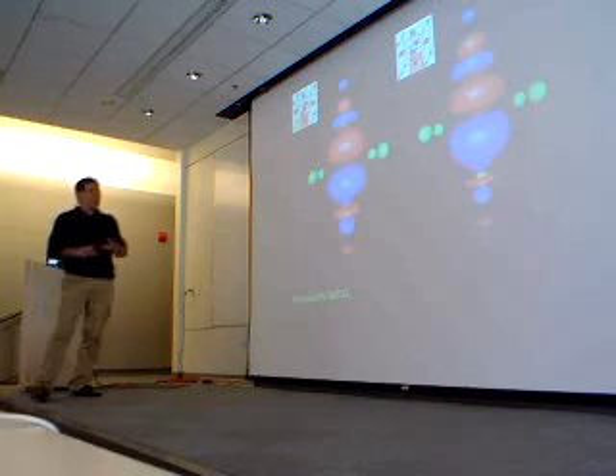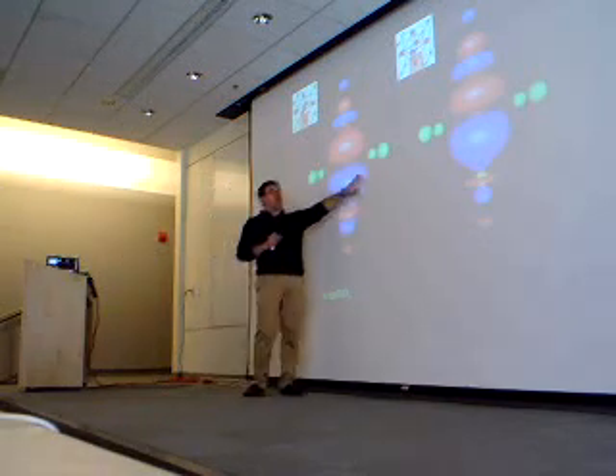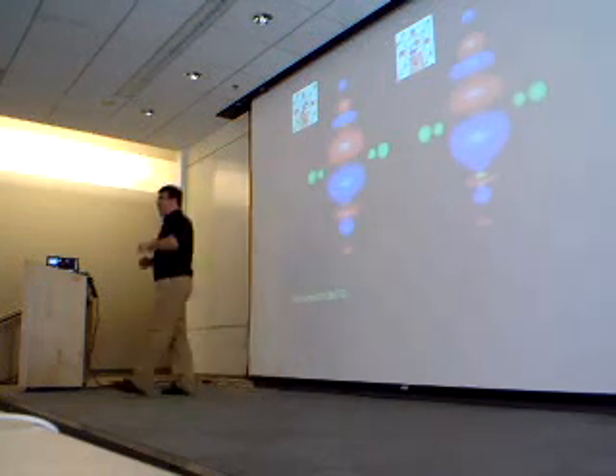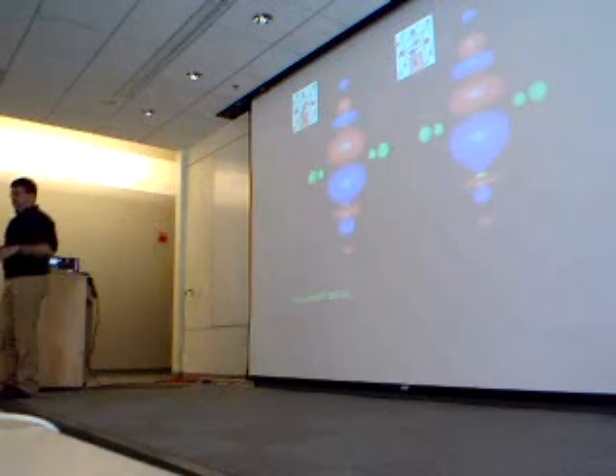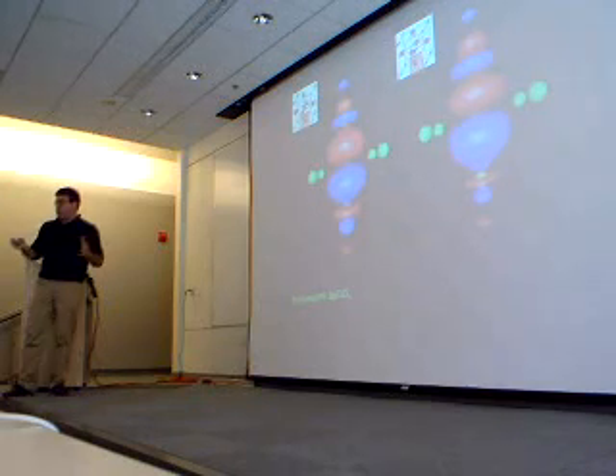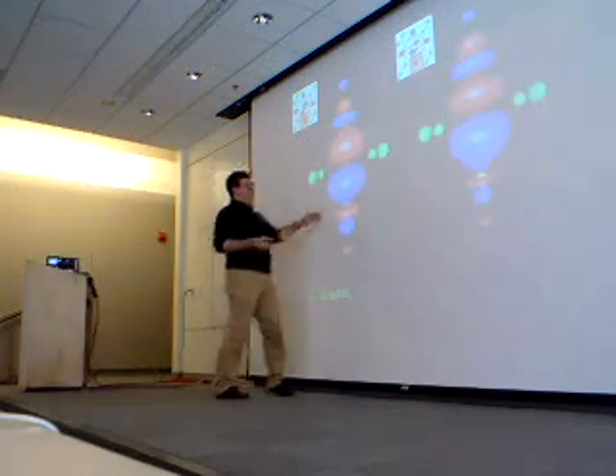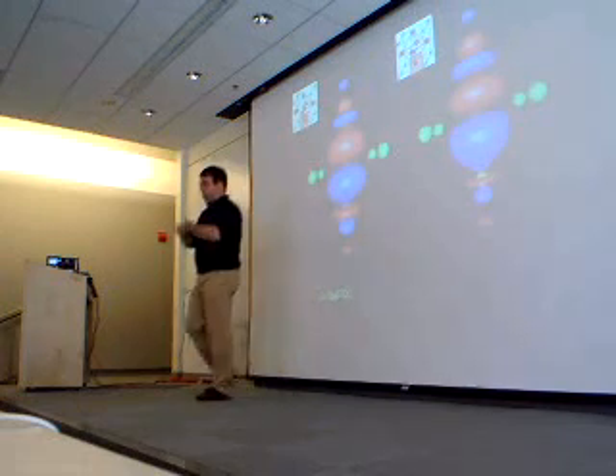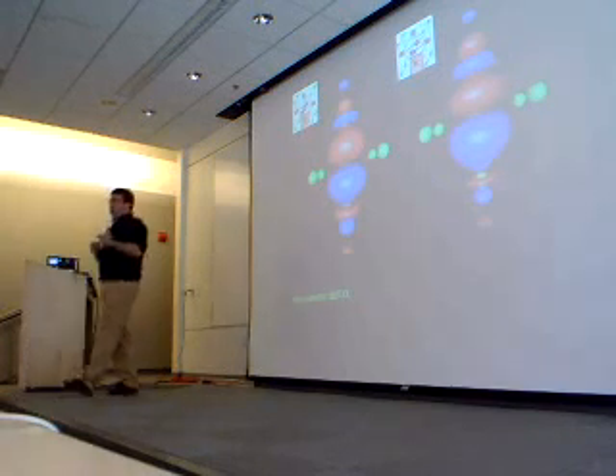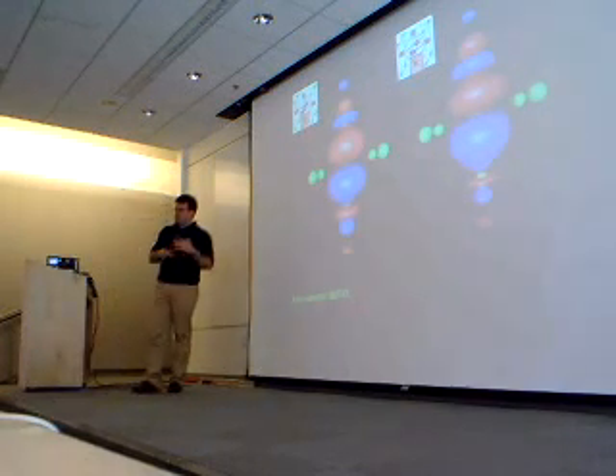So an infinitesimal electric field can create a huge polarization, but that is still with effective charges that change only very little. So the effective charges in themselves change very little from one phase to the other, but of course at the phase transition, the dielectric response, that is a susceptibility, diverges like all response functions diverge at a phase transition. And then the fact that it's not divergent is only related to the nucleation cost and the fact that there is an interface, and so it's really related to the cost of moving the domain wall boundaries between the ferroelectric and the paraelectric phase.